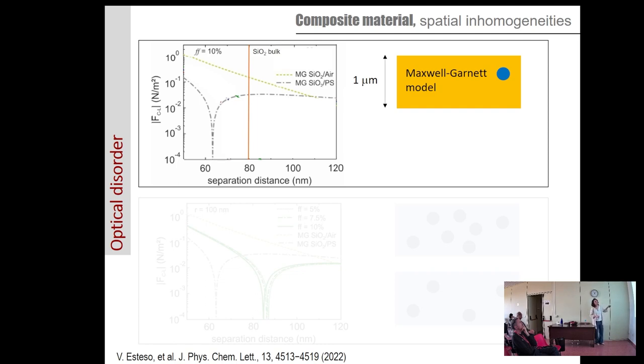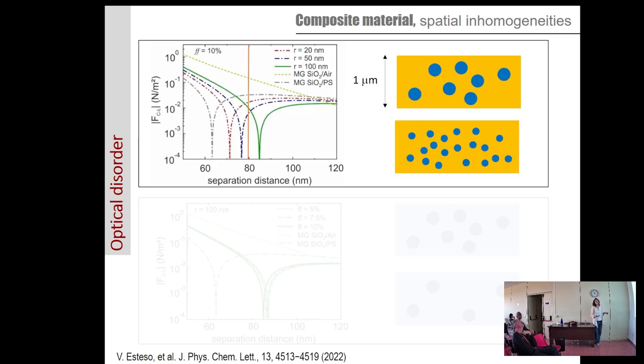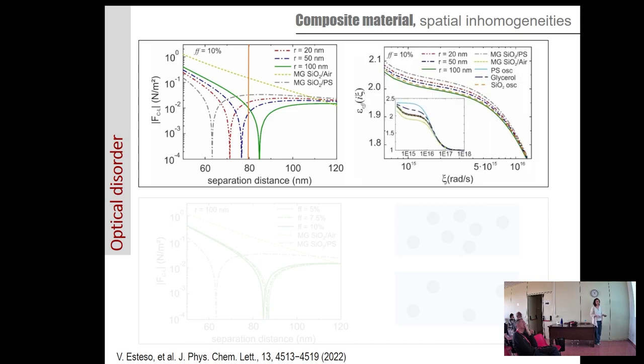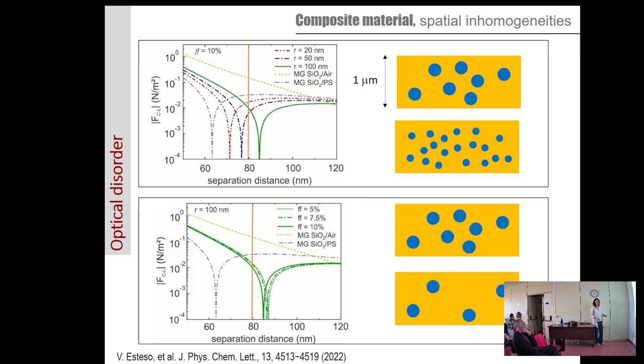So if you consider an effective medium approximation for a 1 micron film thickness with this amount of spheres, this is what we get for silica and polystyrene, and this is fixed. But if we consider the size of our particles, then we get these different equilibrium positions when the particle is really taken into account in the model. And we, well, this is the kind of curves that we analyze, and we do the same by just changing the concentration of the spheres.